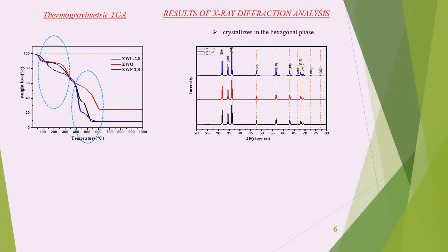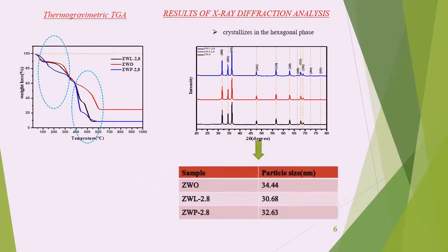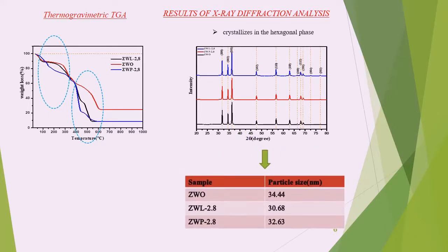X-ray diffraction analysis of the obtained samples showed that all peaks are in good agreement with hexagonal zinc oxide. It is clear that there are no peaks corresponding to other phases, confirming the pure phase of prepared zinc oxide. The particle size can be calculated from the diffraction pattern using the Debye-Scherrer formula.